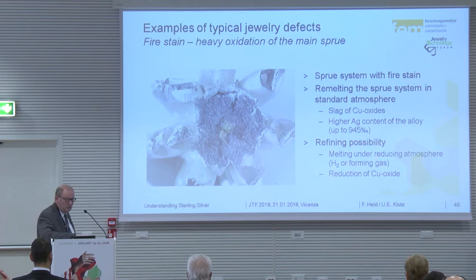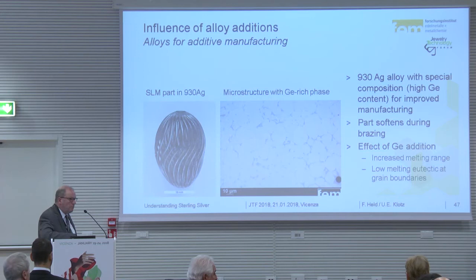But what he had done is copper slag was in the crucible and the melt he had cast was only up to 945 silver containing, and then you lost the feeling about the casting temperature. How can you do it? Make a refining under forming gas or pure hydrogen. Forming gas will be enough during melting and copper will reduce, so you keep the copper as copper in your material.